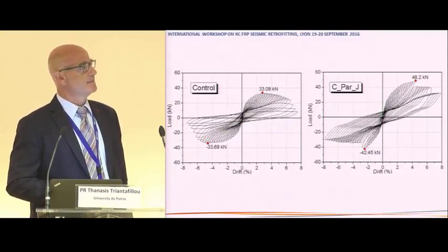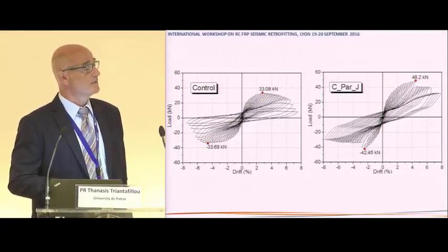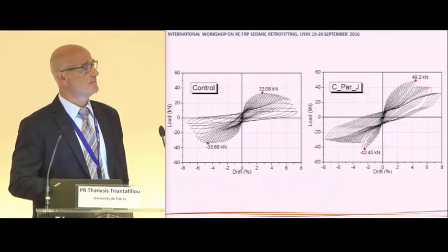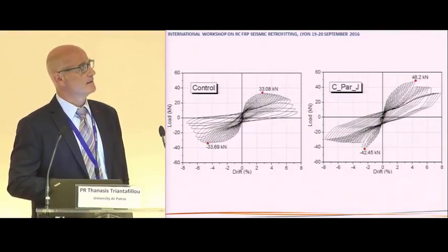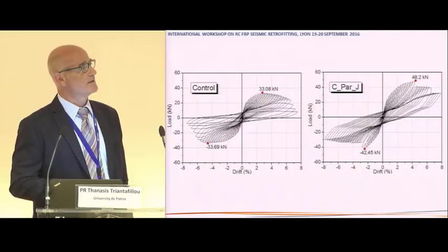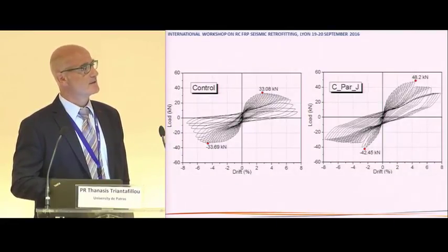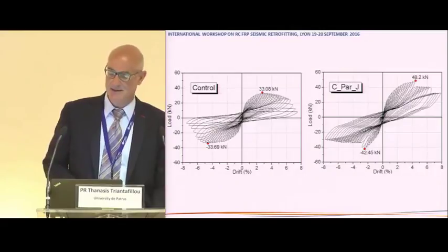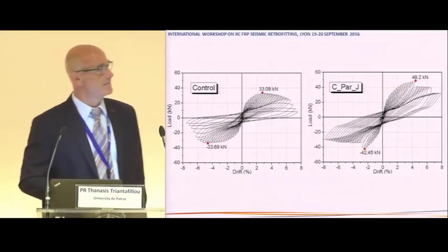And that's a typical comparison of a reinforced concrete column, flexurally strengthened with FRPs. That's a control specimen that is prior to adding the flexural reinforcement, and this is what we get by an identical specimen with this extra externally applied reinforcement. There is an increase in the strength, but practically no increase at all in the stiffness.